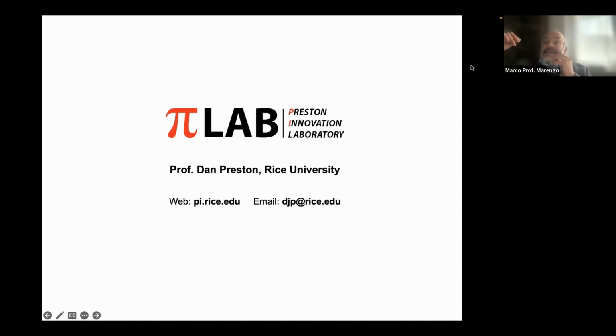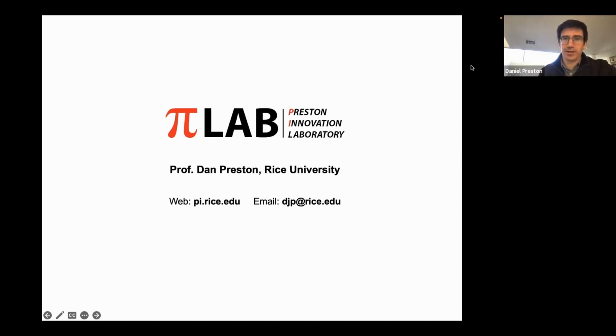I don't know. Yeah, this is something we noticed from some of the IR imaging: the surface gets hot much faster when we have the insulation layer and remains hot. I think that it is not able to fully prevent the evaporation and recondensation, but it can make it much smaller, orders of magnitude smaller in rate.